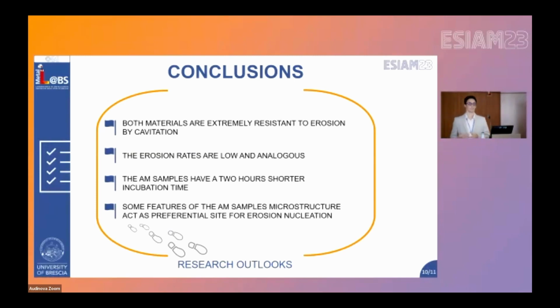So we can say that a component generated by laser powder bed fusion could compete with a forged one as regards cavitation erosion. And for further research, tests could be done for shorter time intervals near the incubation time to fully establish if the residual austenite is the weak point in the microstructure acting as preferential site.